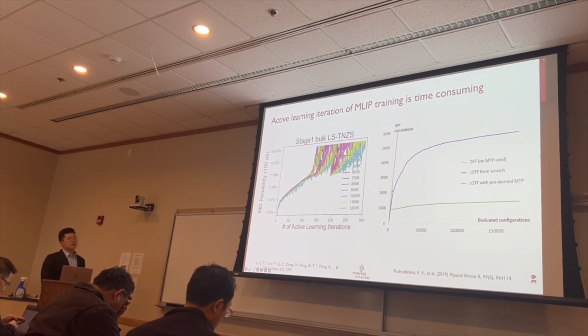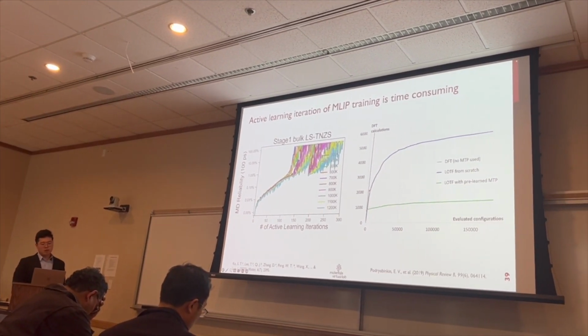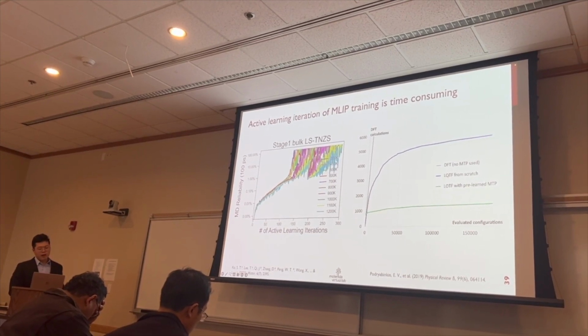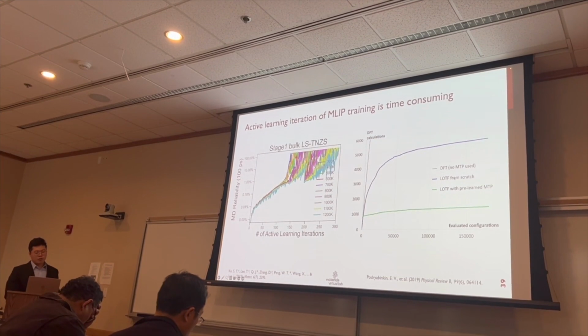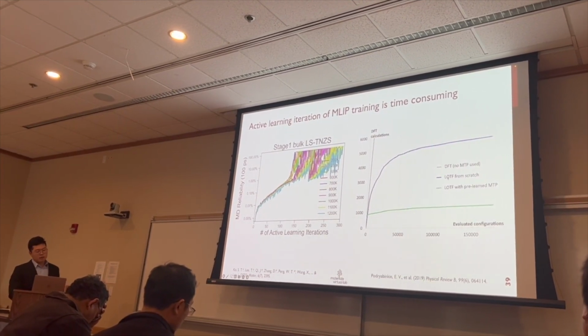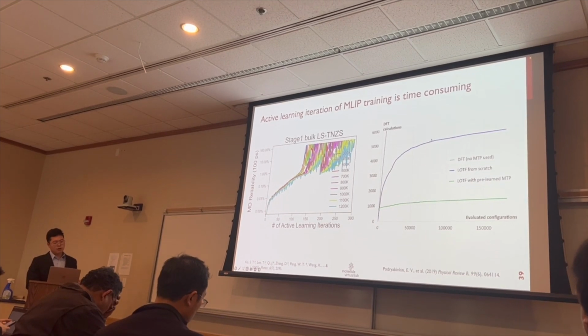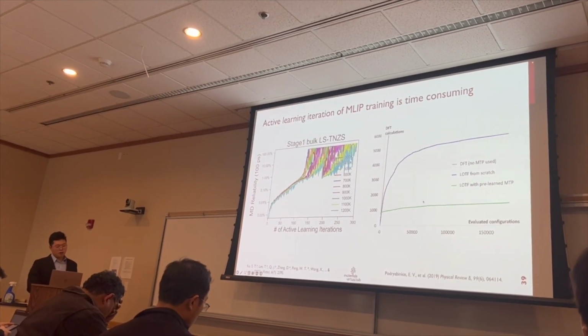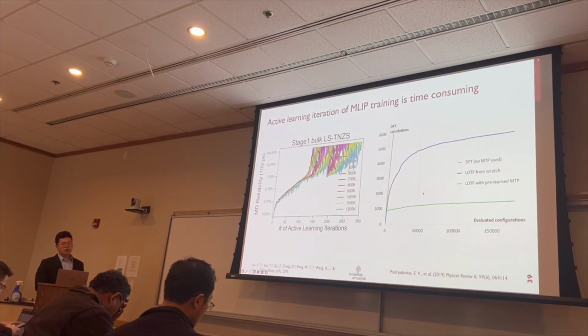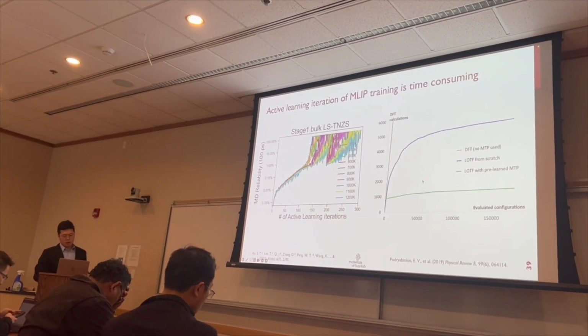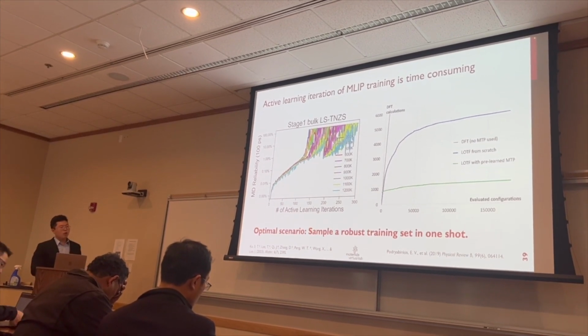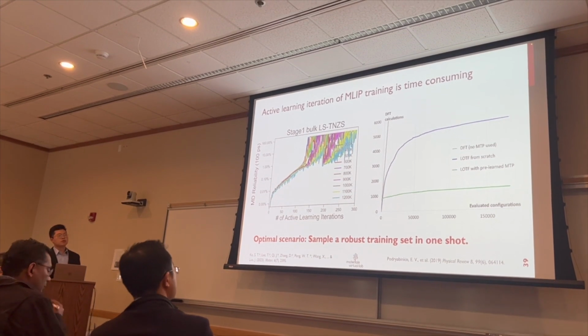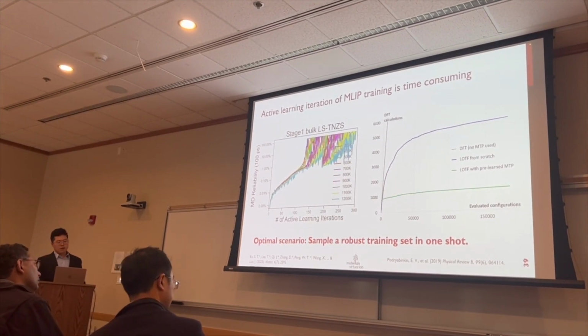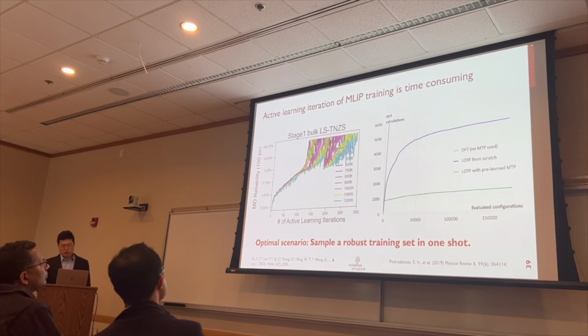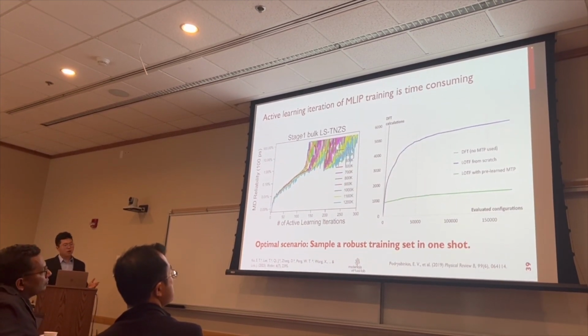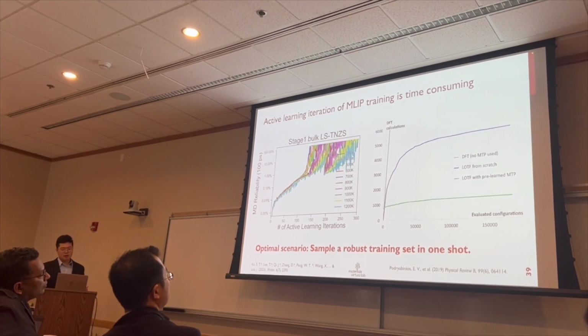And if we look at some results from the MTP developers, you can see that for learning on the fly, which is active learning from scratch or from a selected initial training set, there can be a significant difference in the computational cost. This tells us that it's very crucial to get a good initial training set to get fast active learning convergence. The optimal scenario we can imagine is to sample a robust training structure set in one shot. And we try to achieve this goal with direct sampling coupled with M3GNet molecular dynamics.